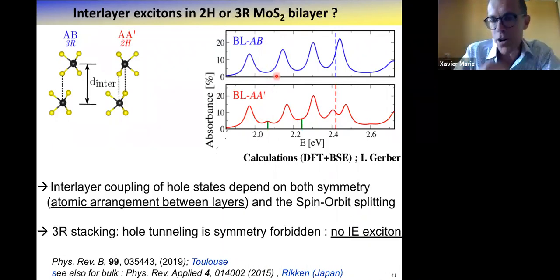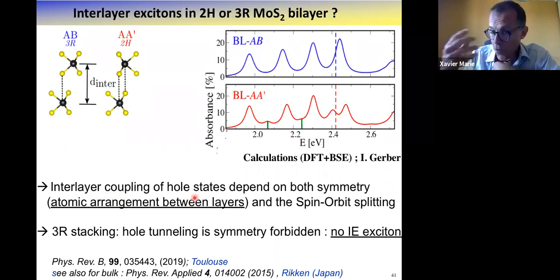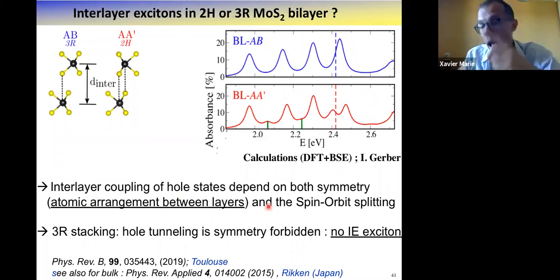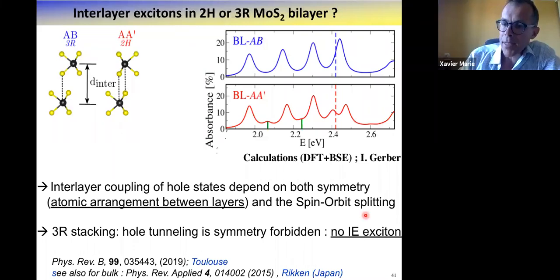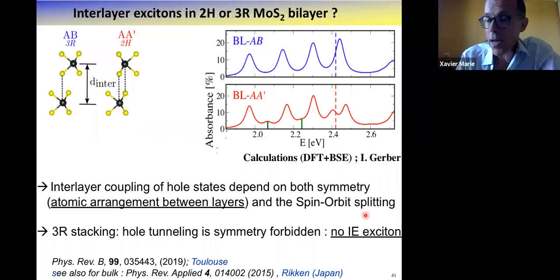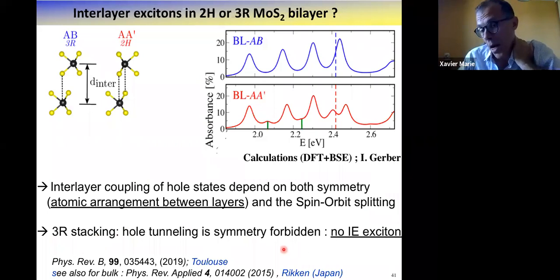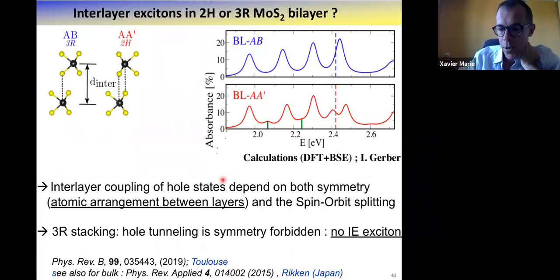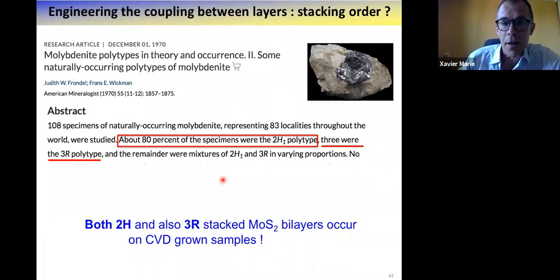And indeed, if you look at the symmetry of the structure and the wave function, you realize that the interlayer coupling of the hole states, which plays a key role in this story, depends on the symmetry and the atomic arrangement between layers, for sure, and also the spin orbit splitting. I will not comment on the spin orbit splitting, but for sure, in W-based bilayers, you expect a weaker interlayer effect compared to MoS2, where, as I said, spin orbit splitting is smaller. But as far as the atomic arrangement between layers, when you look at the symmetry, you realize that with the 3R stacking, the hole tunneling is symmetry forbidden. Because of that, it's not surprising that in sophisticated calculations, you find no interlayer exciton with this stacking. So this is a prediction from calculations. And I will show you now that it works rather well with experiments.